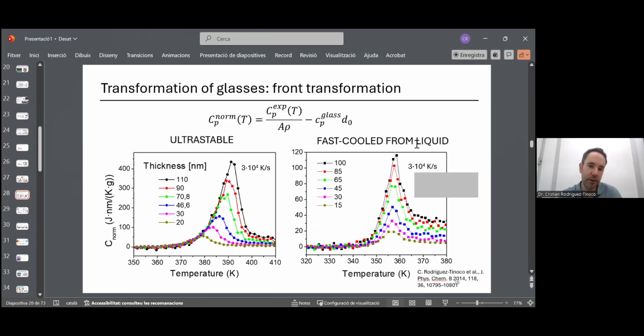Of course, this is the other vitrification. So this is for the ultrastable glass. This is for the fast cooled liquid, the conventional glass. If in a conventional glass we apply the same normalization process, which shouldn't work, because we said a fast cooled glass prepared by quenching from the liquid state transforms via a bulk process. So now it doesn't work because this is not transforming via front propagation. So this is a bulk mechanism.